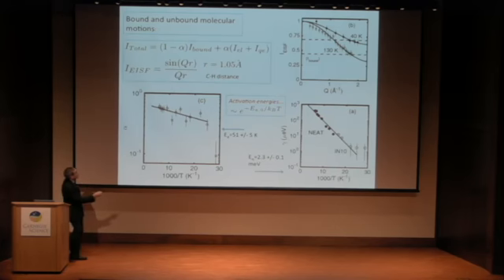You might say, well, this is a bit unfair. Why didn't I go out here to higher Q? It turns out that's a limitation due to the kinematics of the instrumentation, and you also tend to run into problems due to Bragg peaks and other scattering processes. So I'm not trying to hide any data here; this is a limitation of the technique we're using. But from this you see that this fairly simple model captures the decay, but it doesn't fully account for it if it doesn't come all the way down to zero. So we need a baseline to fully account for the data.